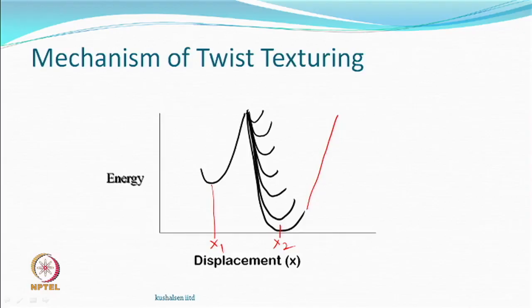We say we do untwisting. When we do untwisting, the energy again goes up because you are acting against the wish of the twisted multifilament yarn. Energy obviously would not like to remain at a higher state and would like to come down. So if you remove the untwisting forces, the yarn would like to go back, and the filaments within the yarn would like to go back to their original position — the helical structure they remember. If all of them go back to position X2, then you again get a multifilament twisted yarn, which is not a textured yarn.